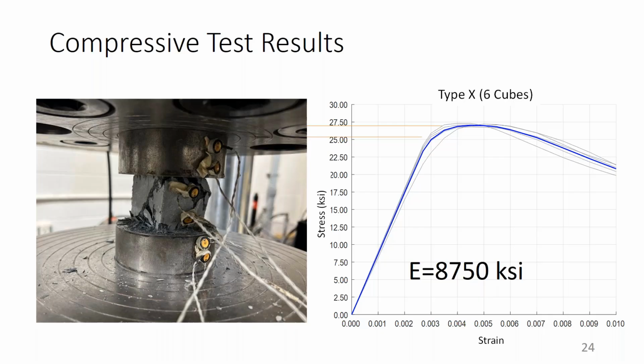Now, as part of this NCHRP project, we conducted testing. So these are compressive tests. You can see that they are made on cubes. The reason we conducted them on cubes was because the third-party testing company did not have the capability to break cylinders. And testing that Ben Graybiel had done had shown that actually the difference between the cubes and the cylinders was pretty small. And so in this particular case, the cubes had a capacity of close to 27.5 KSI, and a Young's modulus of about 8,700 KSI.